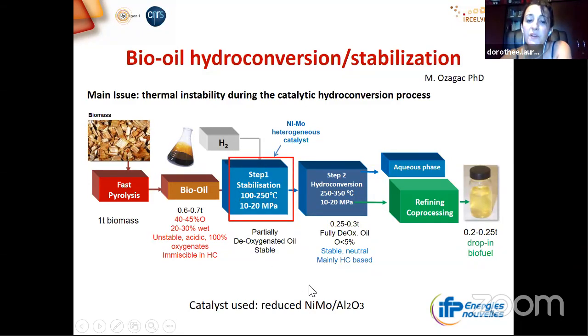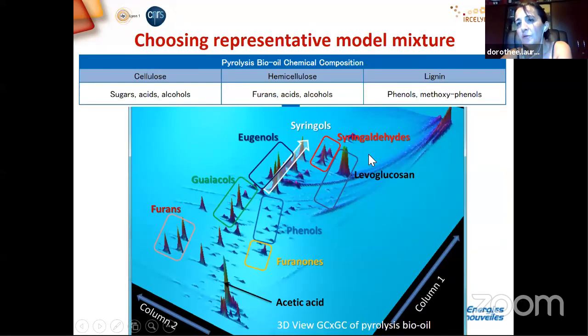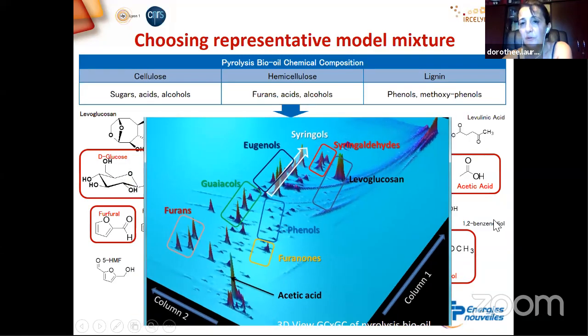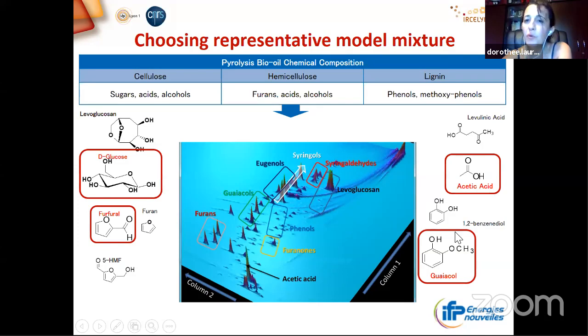So we studied the nickel molybdenum supported on alumina catalyst in reduced form for this first step of stabilization to improve the further hydrotreatment. So in order to choose a representative model molecule for this mixture, we considered the characterization by GCxGC of a pyrolysis bio-oil. So you can see here the various families which are typically found in those bio-oils, like furan, guaiacol, sugars such as levoglucosan, phenol, furanone, acetic acid. And then we have chosen glucose, furfural, acetic acid, and guaiacol as the four model molecules, and we also used water to make some blended mixtures.